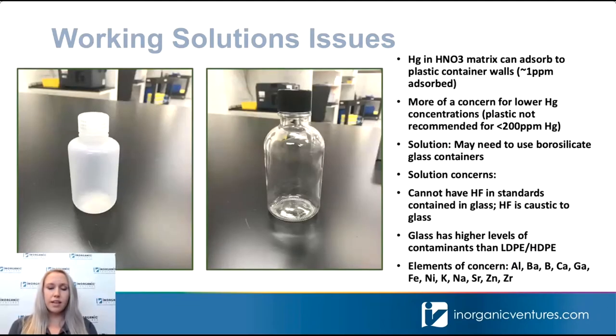Again, in a nitric acid matrix alone, mercury will adsorb to plastic components. This includes container walls. We've seen that approximately 1 ppm is adsorbed to the insides of the container walls. This is going to be a much greater concern for low levels of mercury, as 1 ppm is going to have a much higher effect on the concentration of mercury at less than 200 ppm.